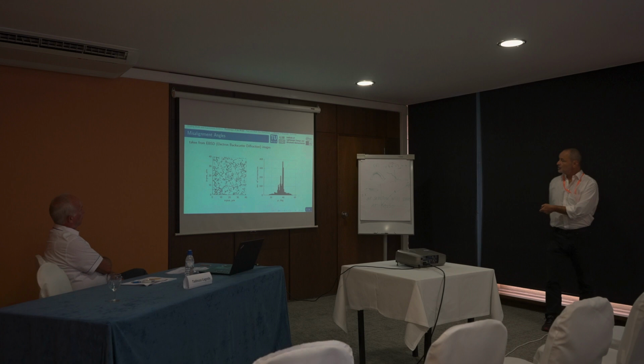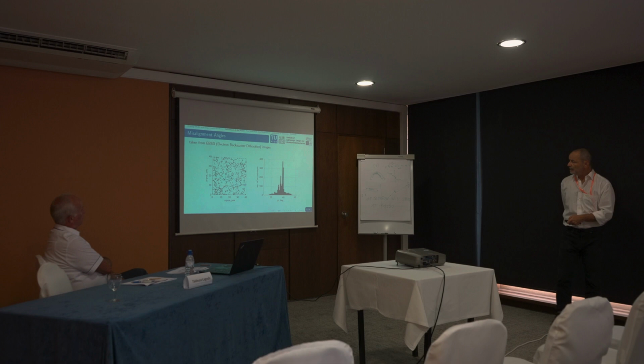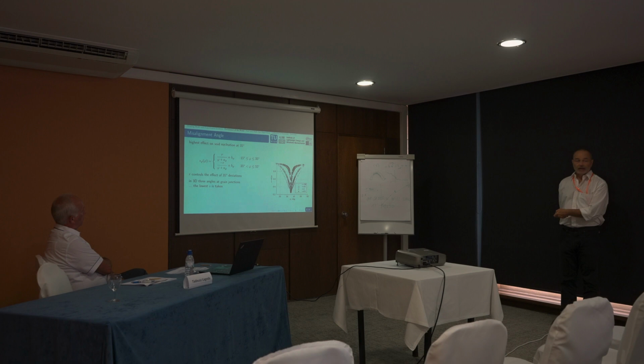So the second information is the misalignment angles taken from EBSD pictures. And you see that there's a certain distribution. And we have a second parameter, which we call R. And we know from initial studies that the most severe misalignment angle is 35 degrees. And for this, we set our value S to 0.25. Ran some studies to find some magnitudes of these values. And this function here takes into account how much angles which are not 35 degrees have an influence on this factor S reducing the fatigue initiation.